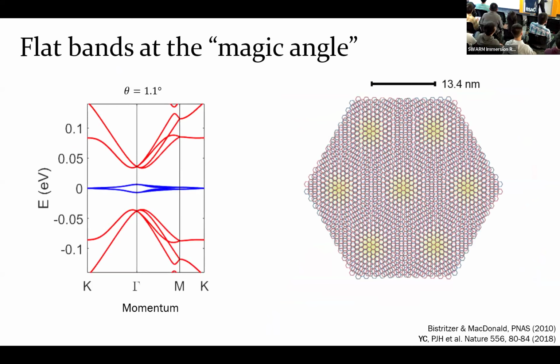So what happens when you twist two layers of graphene is that at this specific angle called the magic angle, when the two layers are twisted by 1.1 degrees, the electrons in graphene do not move in the Dirac cone that I showed you before anymore, but instead they form these so-called flat bands. And if you recall that the velocity of an electron is related to the slope of these energy bands in the momentum space, having this flat band really means that electrons become very slow in the lattice.